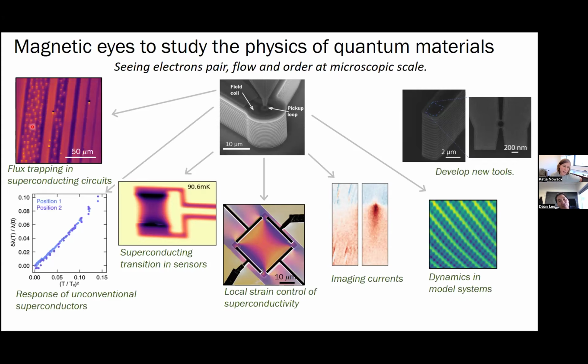The way we take these images is, we have actually a big coil around our cryostat that can apply magnetic fields, but just not very high fields. So we apply on the order of maybe 200 microtesla. Keep in mind, even Earth's magnetic field is about 50 microtesla, depends on where you live, but that's the order. And so if you just do nothing and cool down a superconducting thin film, you have a lot of vortices in that film already. Actually, it's the opposite. We typically first need to screen our systems so that we don't get too many vortices. And then we have an additional coil to actually apply a little bit of field. Or we compensate the Earth field and whatnot. But the field scale in this kind of image is maybe, I would guess, like 40 microtesla or so. And that we just apply with a very large solenoid.